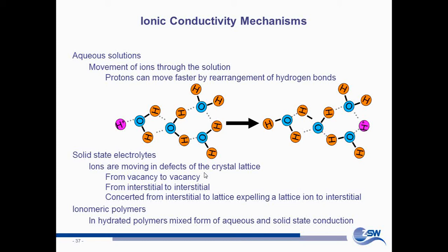In the polymer electrolyte membranes we are talking about today, it's like in the aqueous. It's not small polaron hopping. Small polaron hopping is involved as well, but the extra speed that these protons or OH minuses are picking up is due to the Grotthuss mechanism, and this is not due to hopping, but